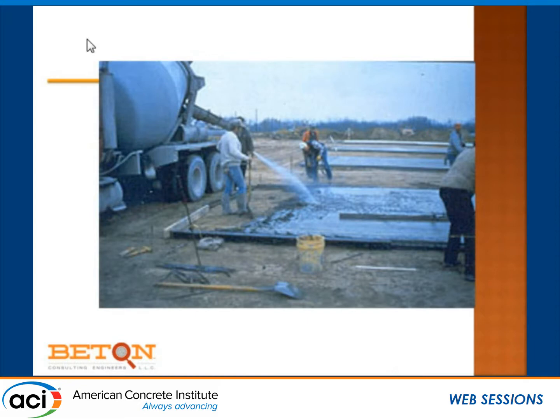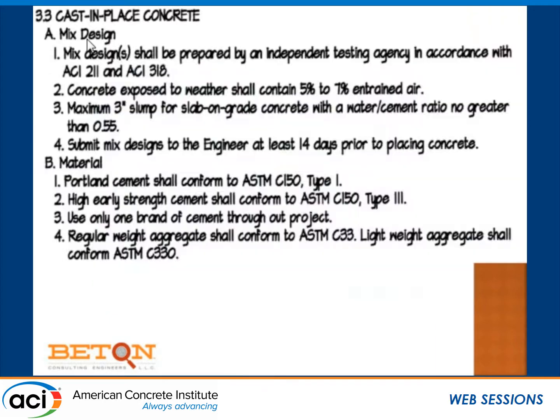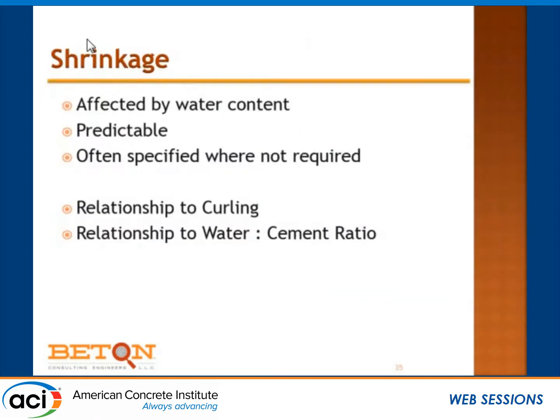So figures never lie, but liars figure, sort of thing, right? And so we get these specifications as we go along. The biggest one that we run into is that we specify a water to cement ratio, expecting it to have an effect on the shrinkage. And the shrinkage is determined by the water content of the mixture and the pozzolan content. It's predictable. If you have any data on shrinkage and mixes, you can take them from all across the country.